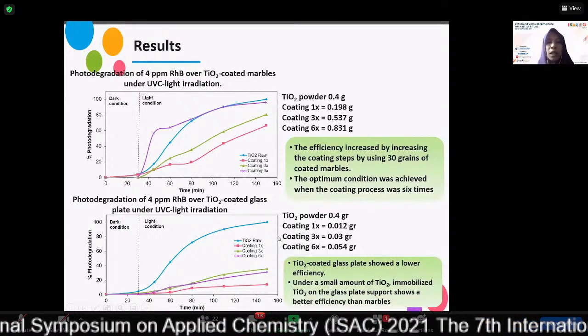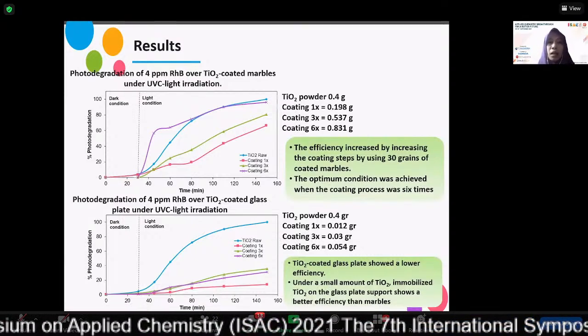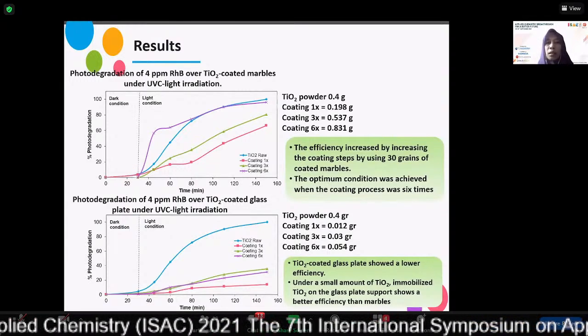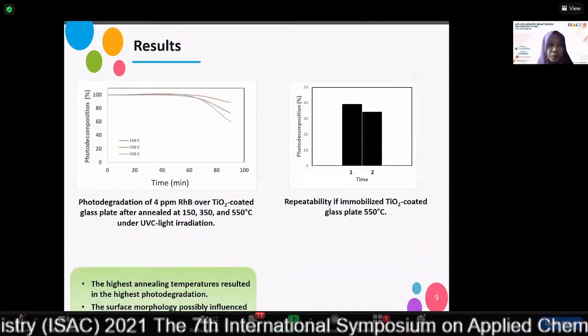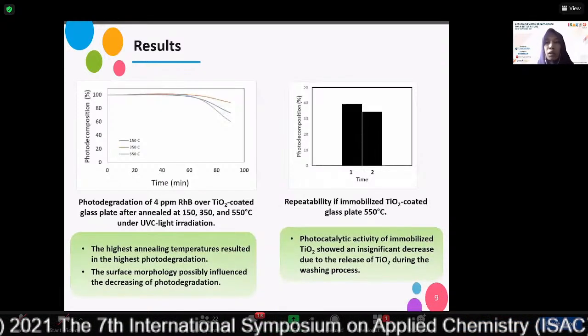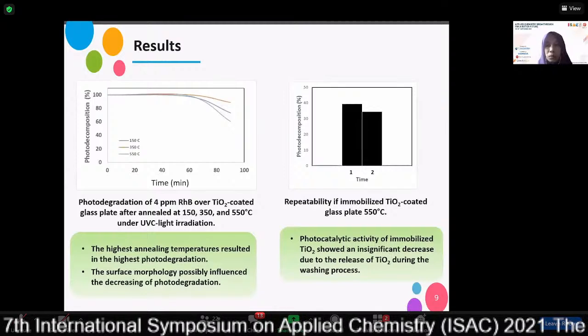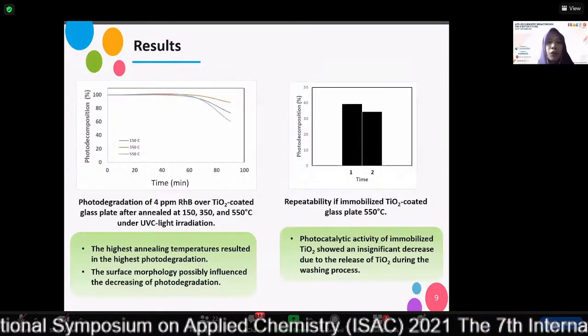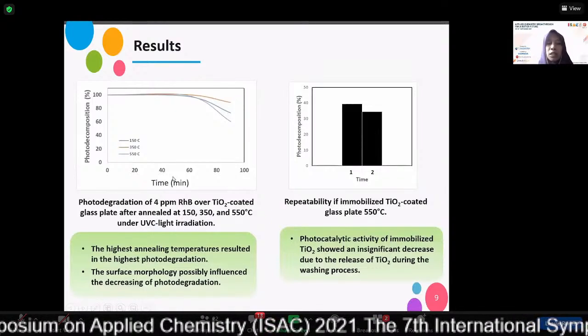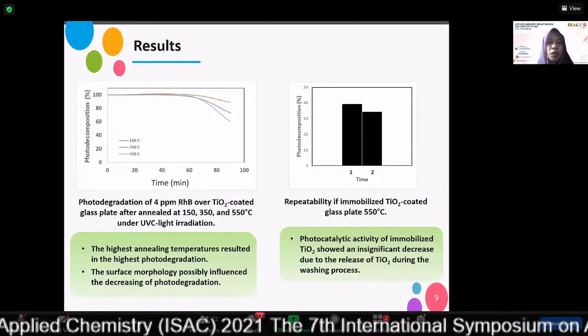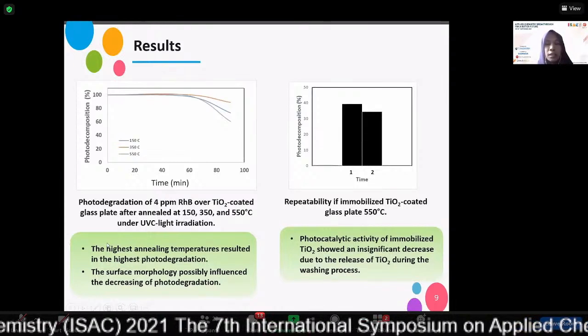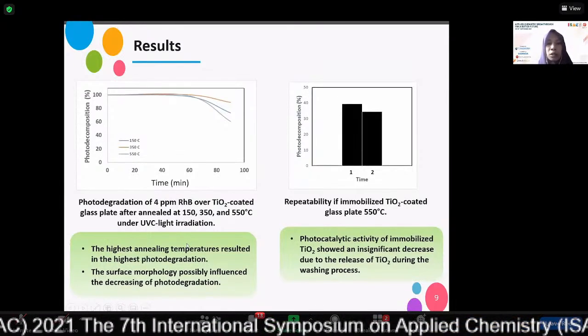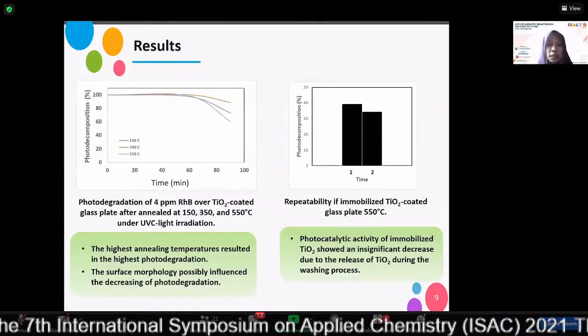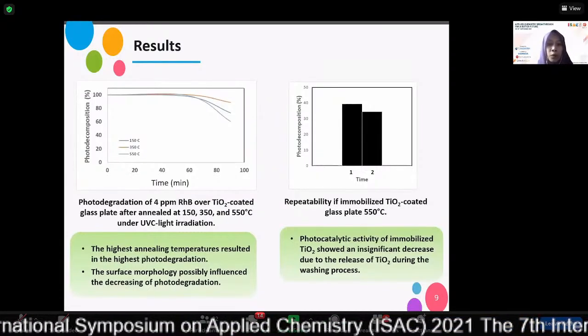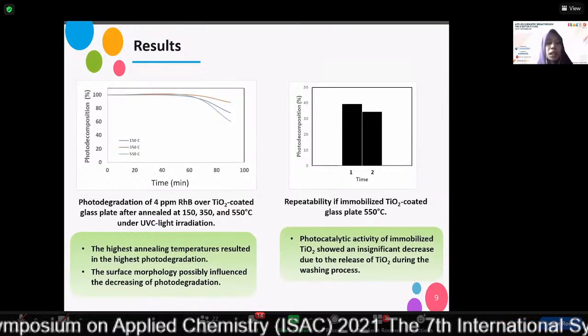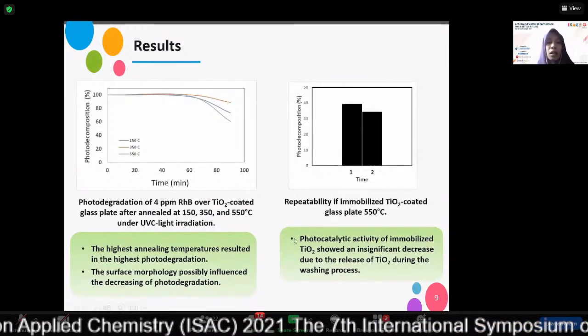This is so that the glass plate is better than the marbles plate. We also study the effect of annealing temperature on the photodegradation of Rhodamine B over TiO2 coated glass plate, and the results show that the highest annealing temperature resulted in the highest photodegradation, and the surface morphology possibly influences the decrease of photodegradation.